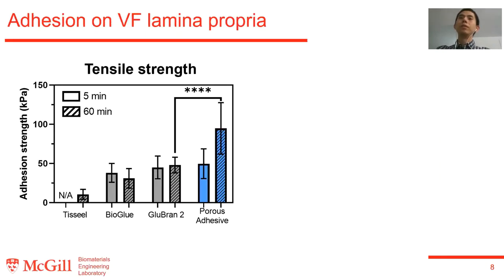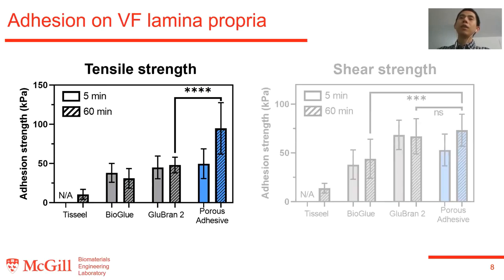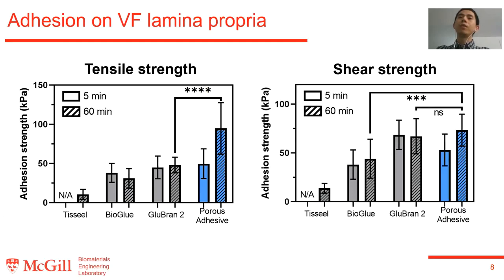We compared the adhesive strength of our porous adhesive with the commercial products. As you can see from the tensile strength, the adhesive strength after 5 minutes is already comparable to the GluBran 2. The adhesion strength at 60 minutes continues growing to reach about 95 kilopascal and is significantly higher than that of the 3 commercial products. And similarly, for shear strength, our porous adhesive also achieved high adhesive strength comparable to that of the GluBran 2. It is 1.7 times stronger than the BioGlue and 5 times stronger than the Tisseel.